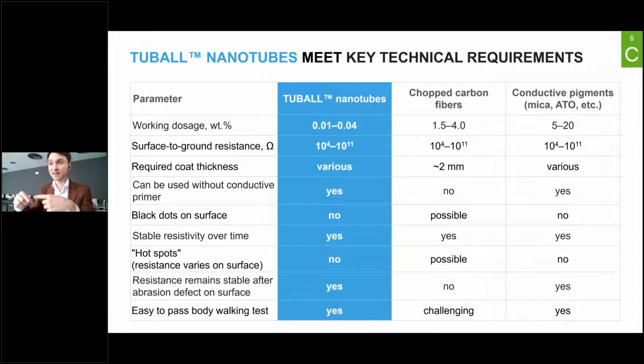So when we started to investigate, it was pretty clear that the servicing company, which was making the application of the top coating, were using conductive primer, which was actually non-conductive. So it was the copper tape, non-conductive primer, and conductive top coating. And of course, our customer was extremely happy because we saved them a lot of money and nervous cells, I would say. So in this case, we can even assist in such kind of cases where there is a risk of non-professional application, because you can fully understand if the top coating would be, in this case, with chopped carbon fibers and non-conductive primer, that even surface to surface conductivity would have never been possible to observe.